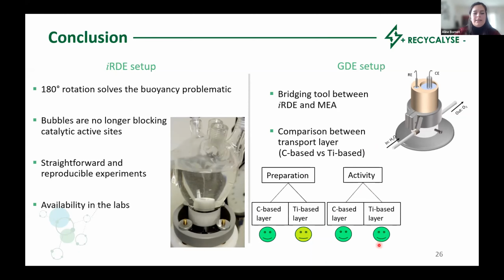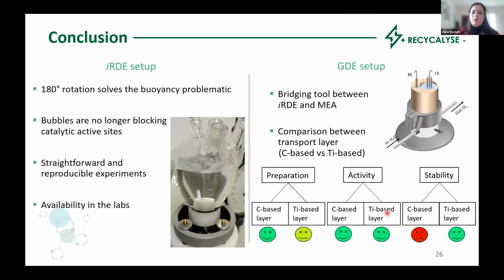Then we see that with both transport layers we can determine the activity. However, if we want to determine the stability of our catalyst, we have to use the titanium-based transport layer as the carbon one is degrading in the course of the measurements.